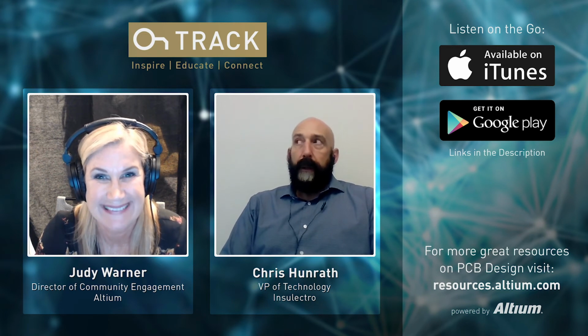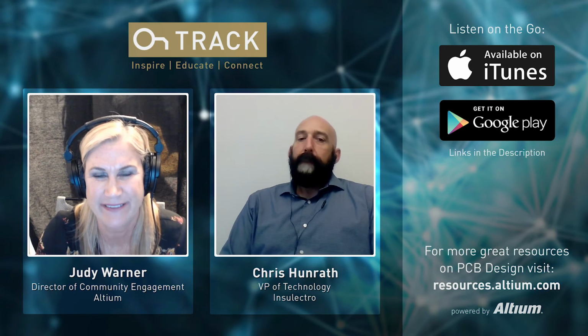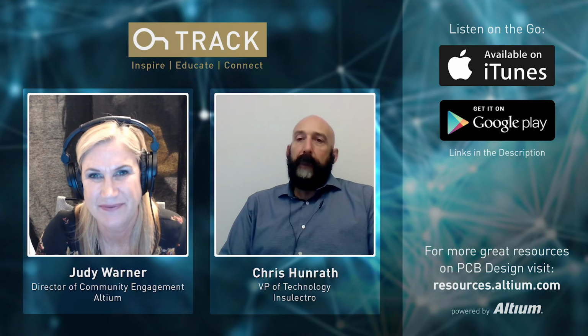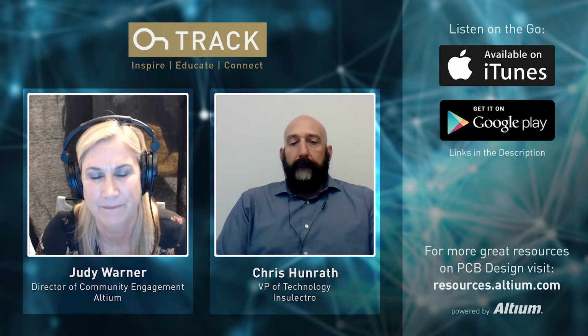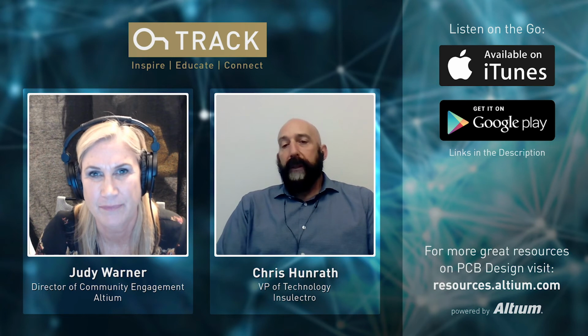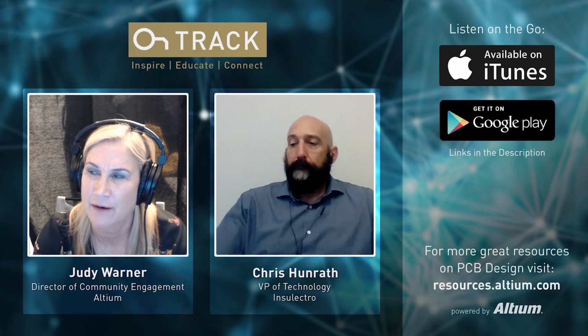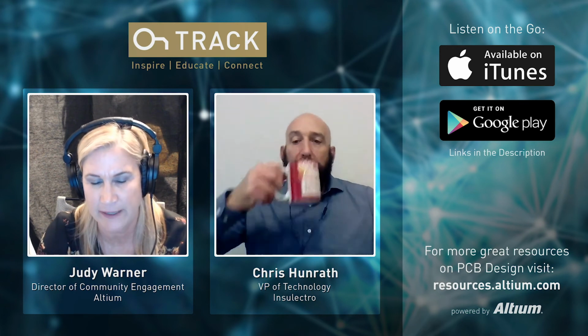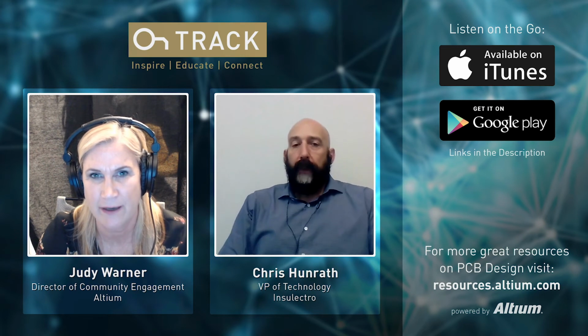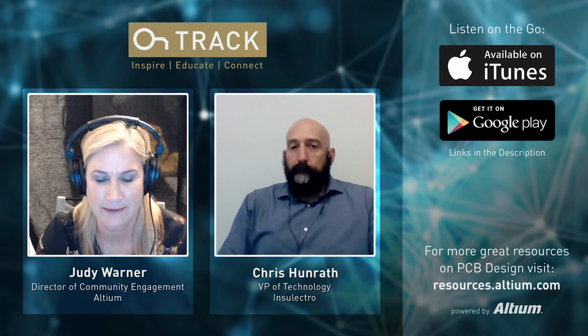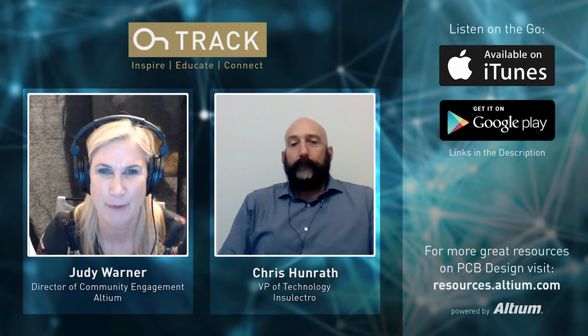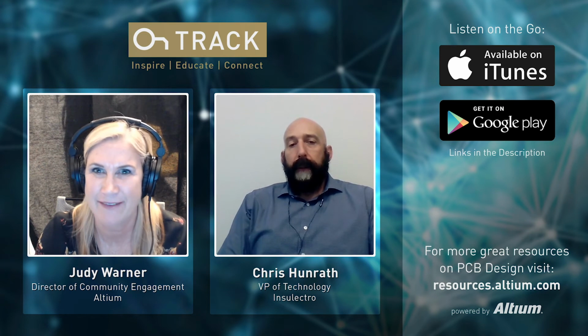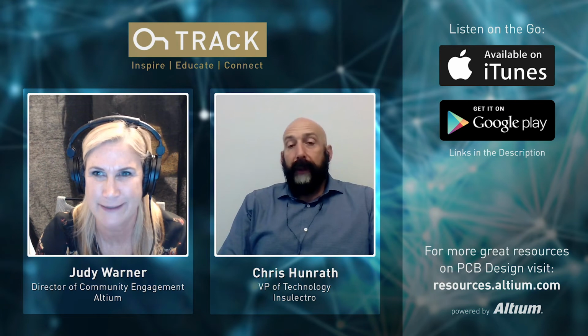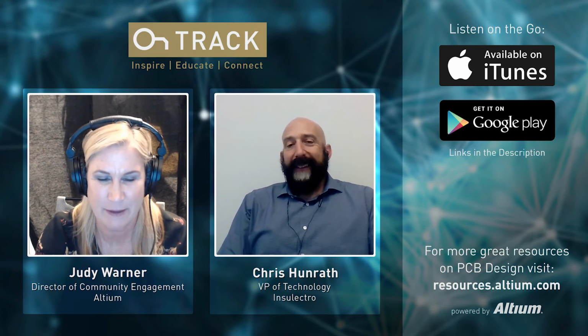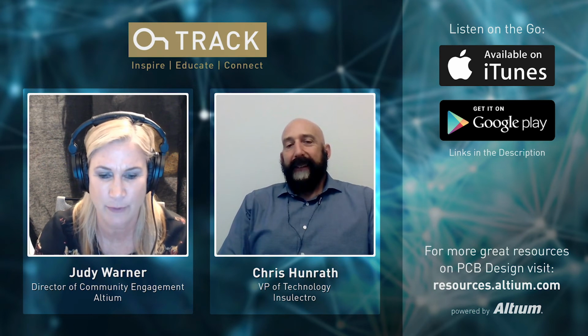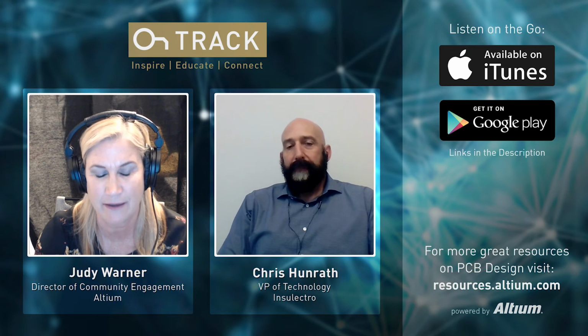Whereas some of the more exotic PCB materials, like PTFE or the filled PTFE systems, LCP, LCP FEP, require much higher laminating temperatures, more like 550 to 600 Fahrenheit. For a while I was at an RF shop, and I'm sure you remember not too many years ago we got on the fusion bonding bandwagon. We thought that was going to solve all our problems, but I remember being at a shop where we were running our lam press at like 700 to 800 degrees Fahrenheit for 12 hours with some crazy profile. That's not very sustainable, but it was a homogeneous Dk, and it had some great performance benefits, but it really never took flight.